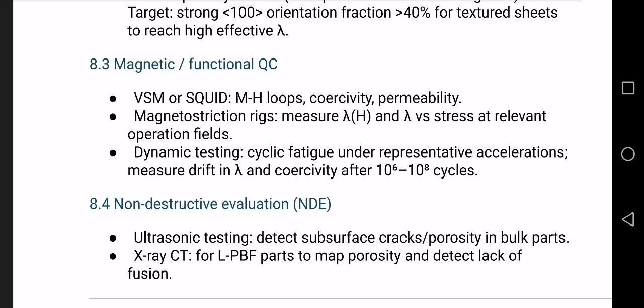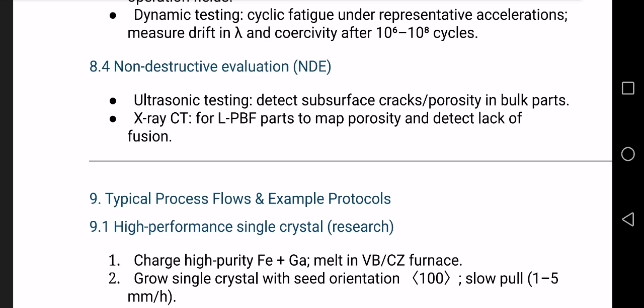Dynamic and fatigue testing. This is extremely important for sensors, and its tests include cyclic loading 10 raised to power 6 to 10 raised to power 8 cycles, measures drift in lambda, checks coercivity and stability. Non-destructive evaluation, NDE. Ultrasonic testing is used for bulk materials, detects internal cracks or voids. X-ray computed tomography, CT, used especially for LPBF parts, and it detects, what does it detect? Porosity, lack of fusion, internal defects.